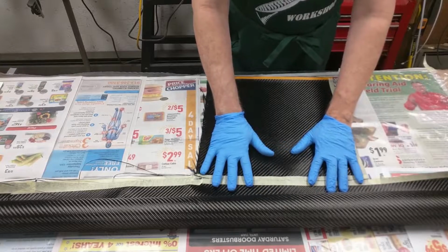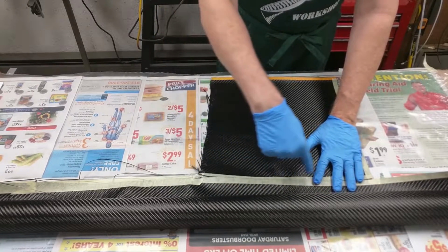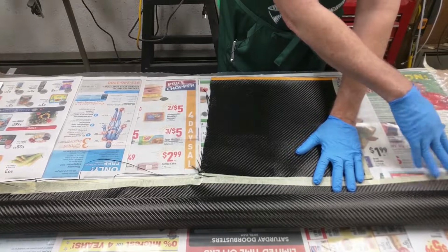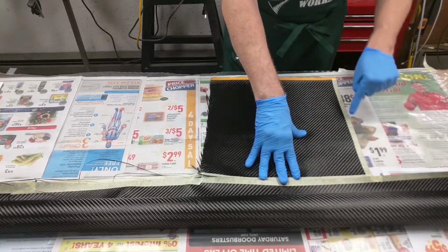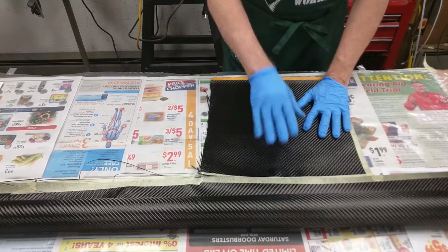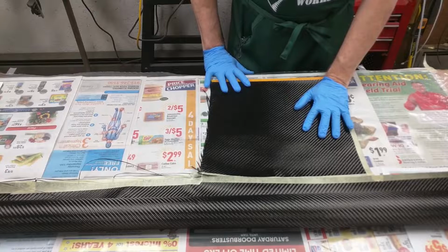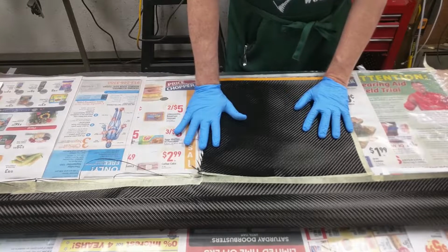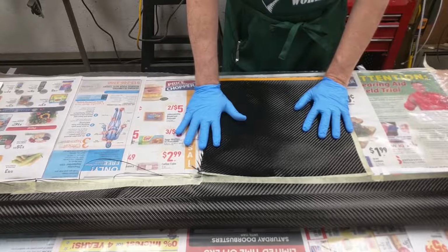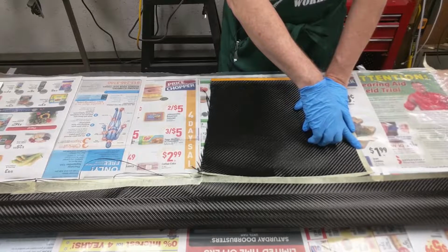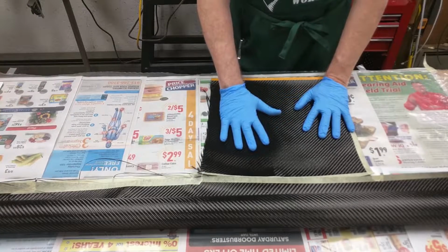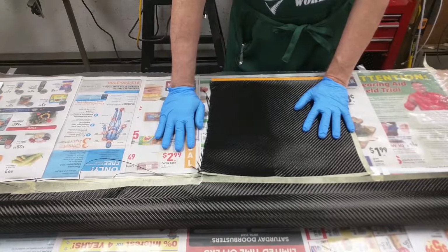So I cut it from this part of the carbon fiber. I laid down a piece of tape, 3/4 inch masking tape, along one edge and then 3/4 down along another edge. I left the original edge that came with the carbon fiber. I did not do one of the edges. The reason for that is I'm not sure when the resin is flowing through this carbon fiber if the adhesive on the tape is going to dissolve and then also flow into the carbon fiber and cause some issues with my epoxy not curing properly or being weaker. So what I'm going to do is I'm going to have the epoxy flow in from this rough edge.